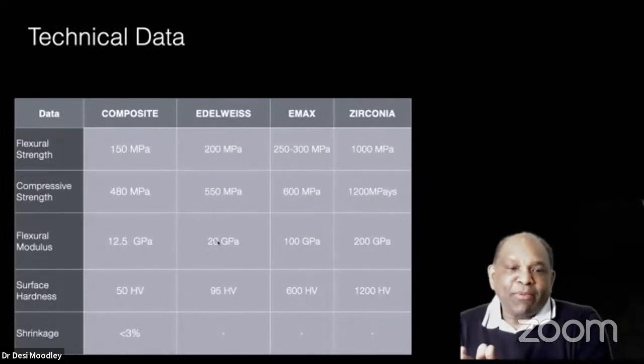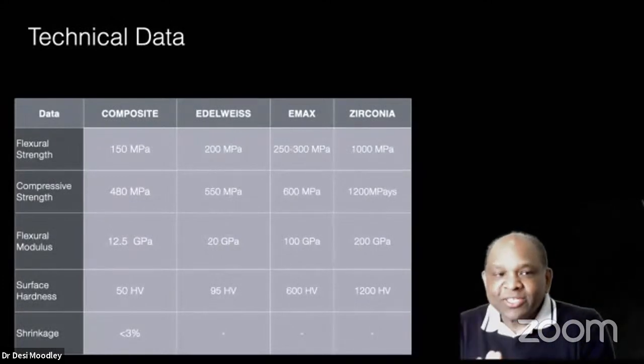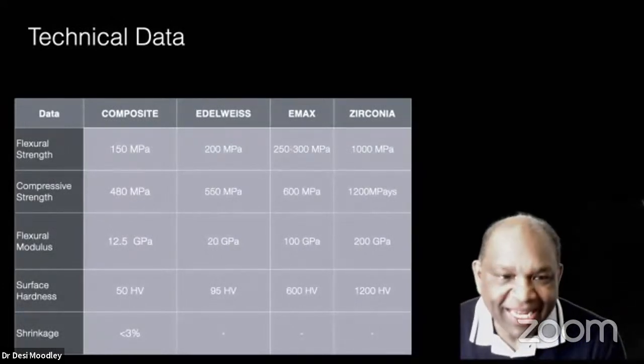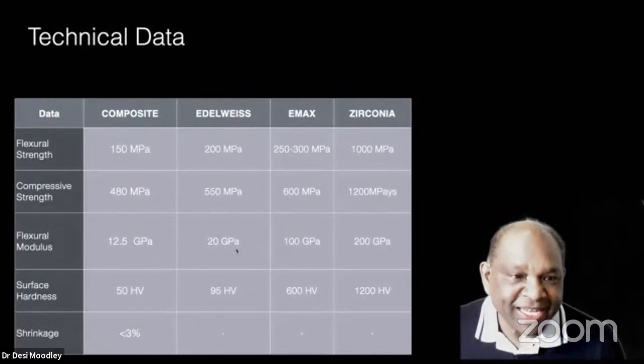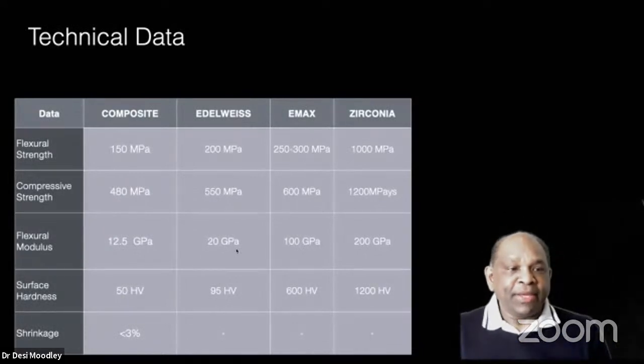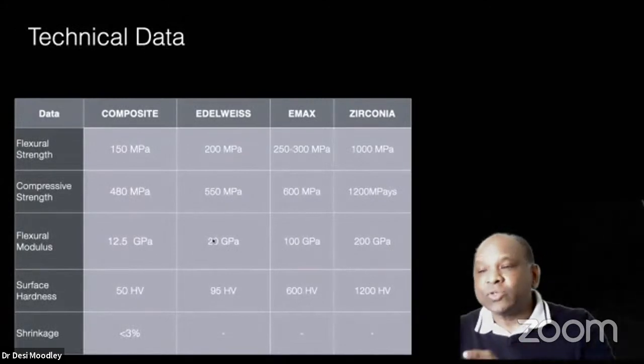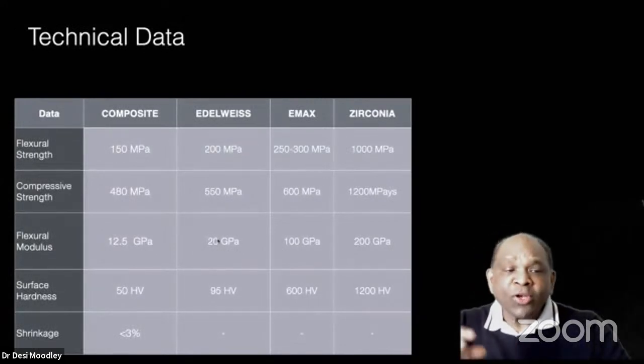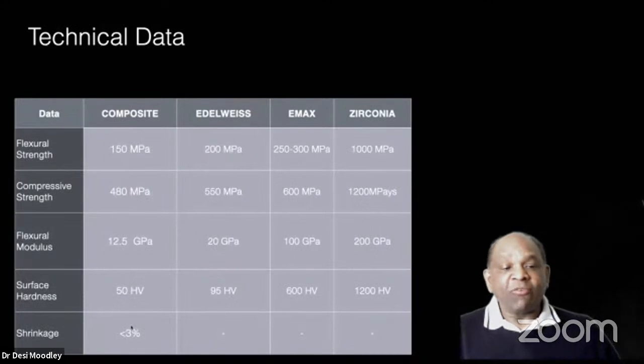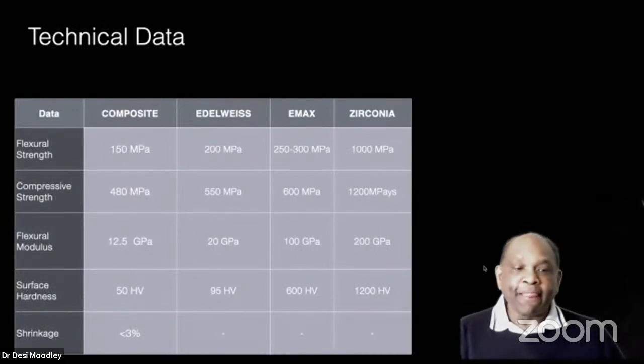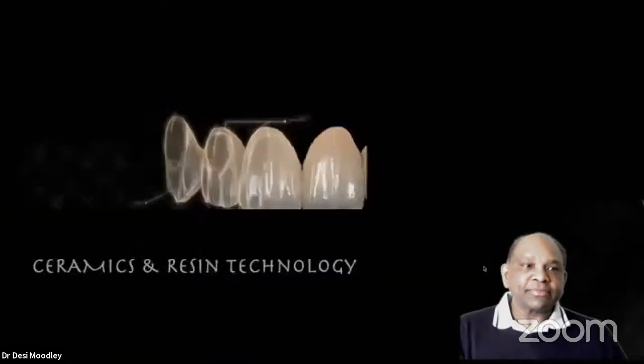But what is quite important is that the flexural modulus, or the modulus of elasticity, is 20 gigapascals, which is close to dentine. So you want to keep that little bit of flexibility. Of course, there's no shrinkage because it's preformed.